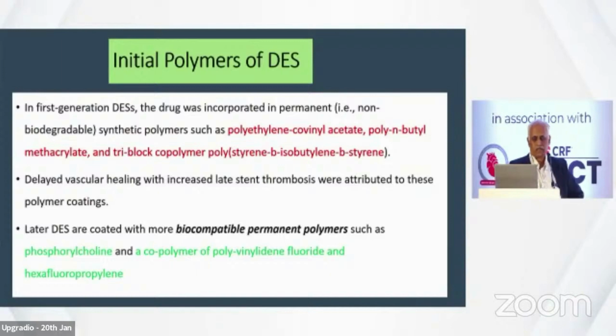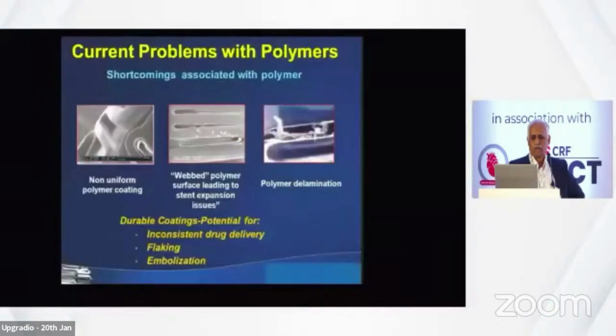So later stents nowadays, we use polyfluorinated polymers, which are highly biocompatible. They use phosphorylcholine, a copolymer of polyvinylidene fluoride and hexafluoropropylene. So these are the commonly used stents. Nowadays, except for the Cypher and Taxus, in most present-day stents the polymer is biocompatible. The polymer on the stent may not have a uniform coating. It may get a webbed polymer surface leading to stent expansion issues, or the polymer may delaminate. So a durable coating has the potential for inconsistent drug delivery, flaking and embolization; these are the problems if your polymer coating is not uniform.